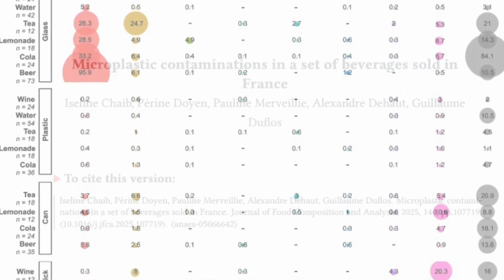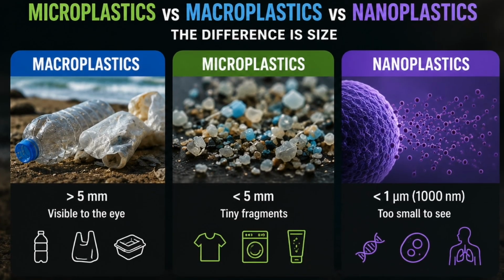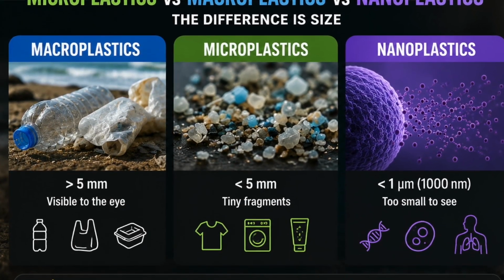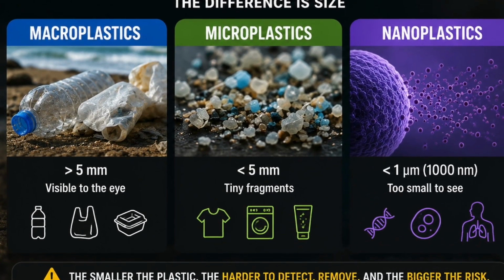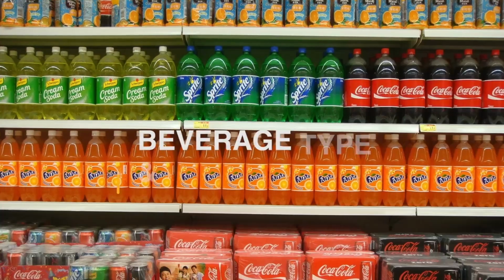The French study mainly counted microplastic down to 10 micrometers. Anything smaller than that, they mostly missed. At that scale, the cap paint on the glass bottle turned out to be a huge source. For plastic bottles, the biggest problem appears at a smaller scale: nanoplastics, leaching from the bottle walls, which this particular method barely sees.